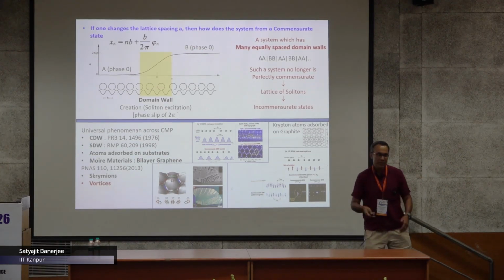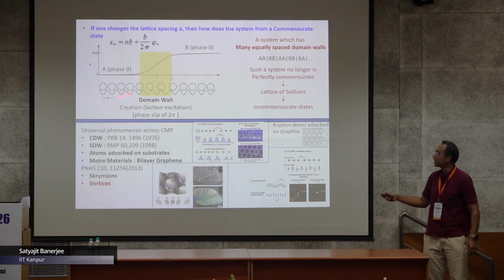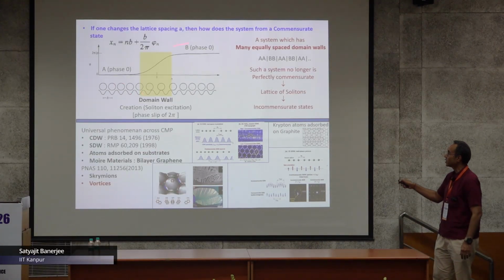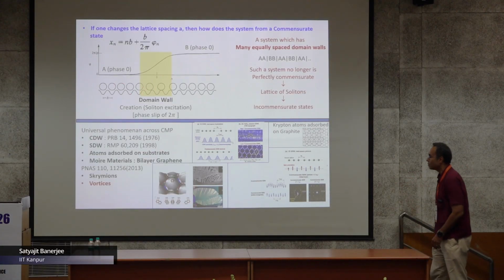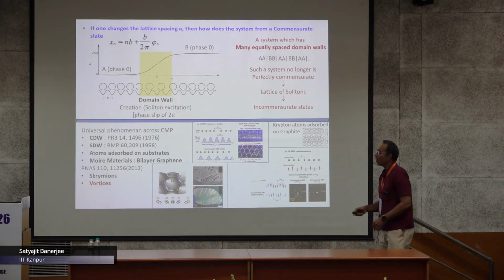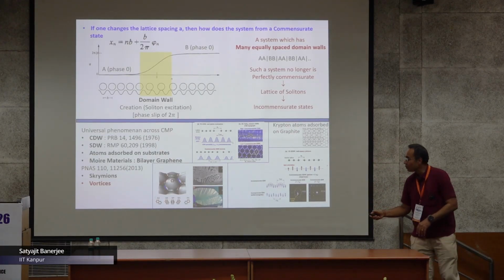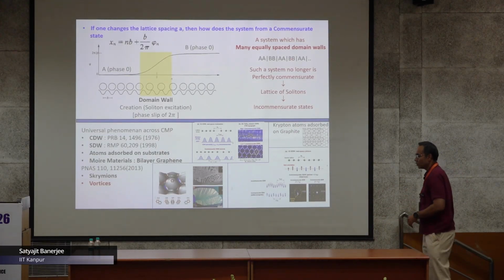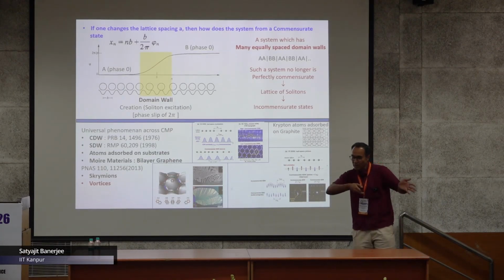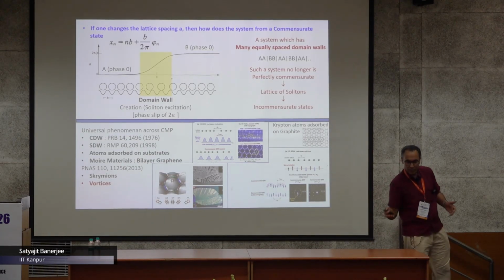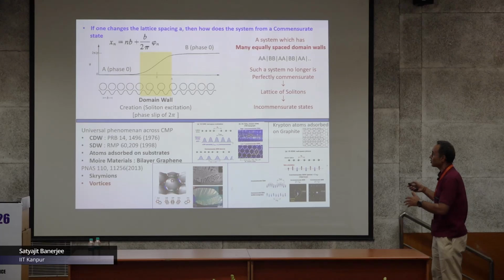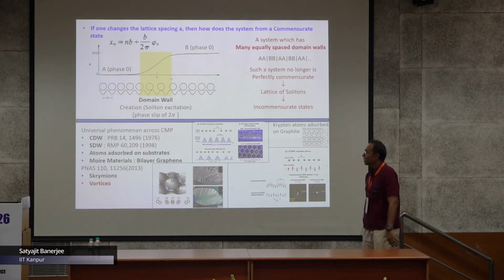These domain walls are called solitonic excitations inside the system. You can have commensurate states separated by domain walls, and if you have a lattice of these domain walls, then you actually start entering into the incommensurate state. So you can get from a commensurate to incommensurate state by creating a lattice of solitons.